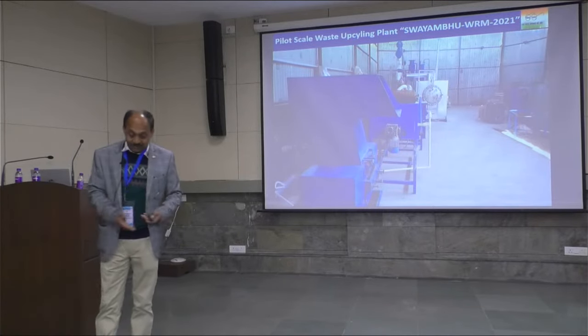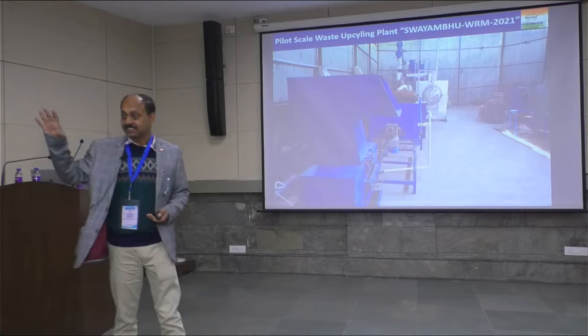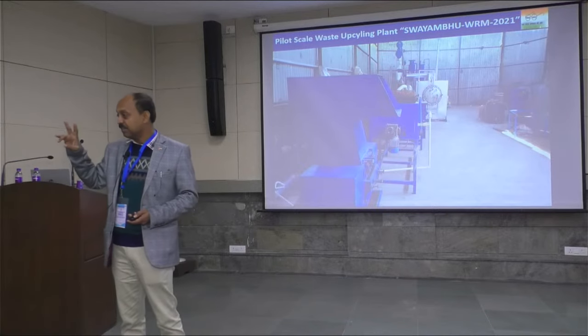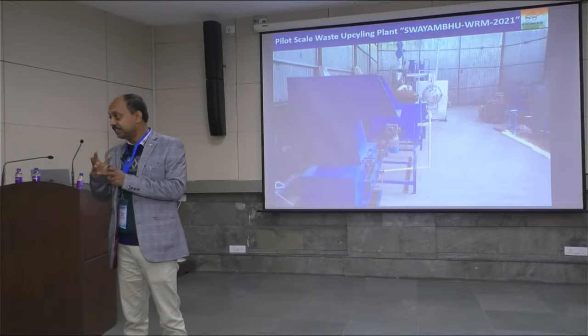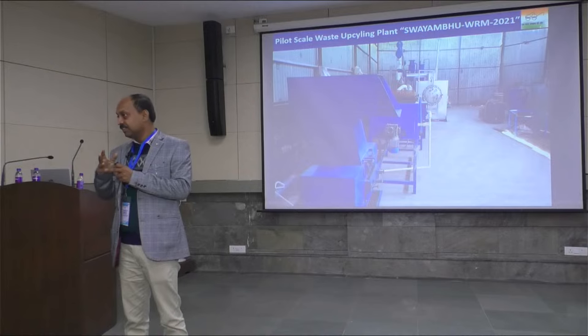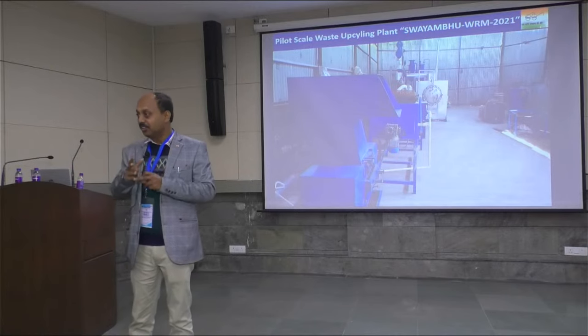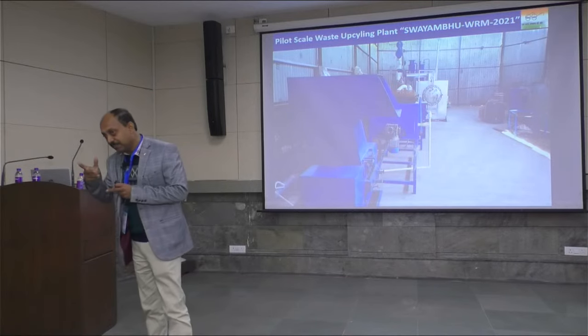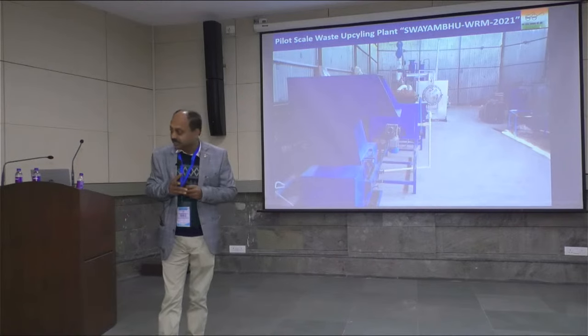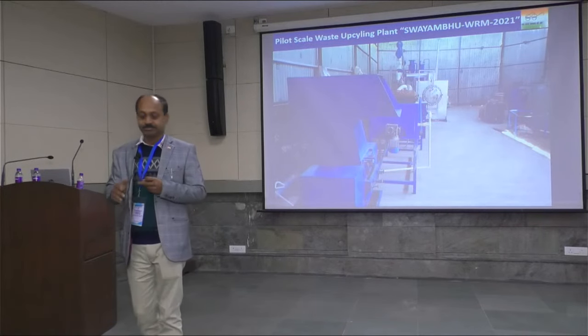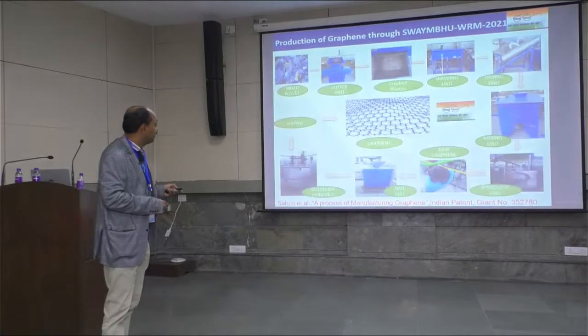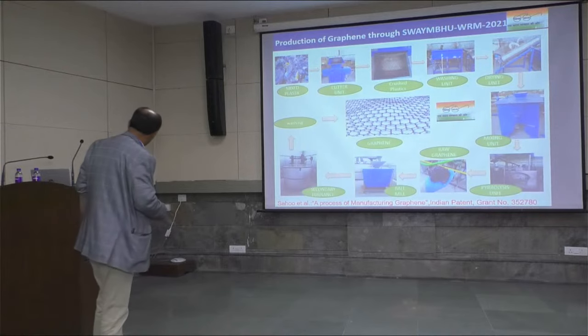Pyrolysis is a very easy procedure. Pyrolysis just took 2 years of time, because it took a time to optimize. If we raise the temperature by 5 degrees centigrade, we don't get good quality. I will show you the whole method of this process.